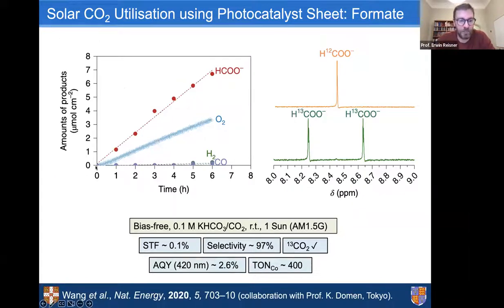The performance here has been very good in terms of selectivity. We can see here the amounts of product versus irradiation time, and it's a very clean generation of formate and oxygen. So this required some optimization, etc. But ultimately, under these conditions, it got quite clean with the expected 2-to-1 ratio, because this is a 2-electron process to reduce CO2 to formate, and it's a 4-electron process to oxidize water to oxygen.